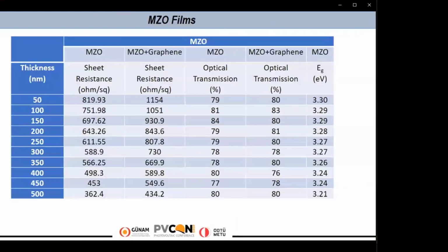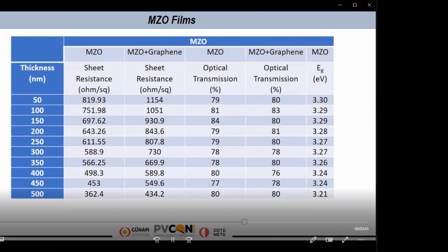When we check the MZO films' optical and electrical properties, when we increase the MZO film thickness, sheet resistance decreases. On the other hand, with increase of MZO film thickness, optical transmission was affected seriously. Generally, MZO films' optical transmission is about 75%. This result can be related to MZO crystalline structure because we observed the same result with aluminum doped zinc oxide and gallium doped zinc oxide. And we know from the literature that when we increase the film thickness, at the same time we enhance the crystallinity. So sheet resistance of MZO can be decreased with increasing film thickness, and optical transmission wasn't affected seriously.